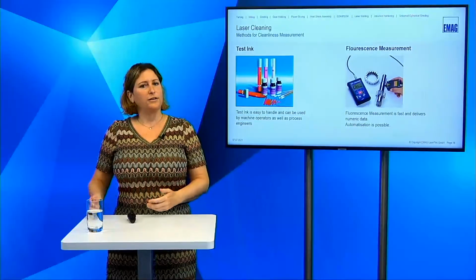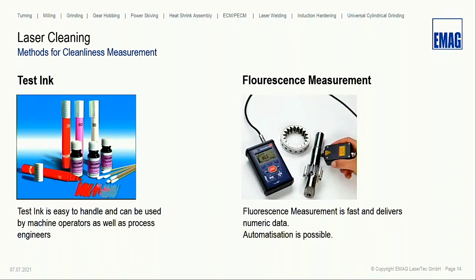We have usually more liquid contaminations on our surface, thus we use the testing or the fluorescence measurements. The testings, as I said, are really easy to handle, and you can nearly measure everywhere with these testings. That's quite nice. For fluorescence measurements, you have a little bit of a problem since you have a certain size of this handheld system, but you can also automate it in a certain range, and you always get a measurement value, so you can compare it over a certain time, and it's always the same.